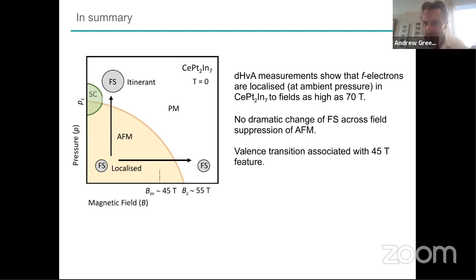So the question I didn't answer was, how does effective mass affect the Fermi surface volume. So the effective mass doesn't affect the Fermi surface volume at all. The de Haas van Alphen effect can measure a number of things. From the frequency of the de Haas van Alphen oscillations, you can get a measure of the Fermi surface area. So the cross-sectional area of the cyclotron orbits on the Fermi surface is proportional to the frequency of the oscillations. And if you change the angle of the magnetic field, then the cyclotron orbits are always perpendicular to the magnetic field, so you can map out what the shape of the Fermi surface is. And effectively, you can measure the size of the Fermi surface in that respect.